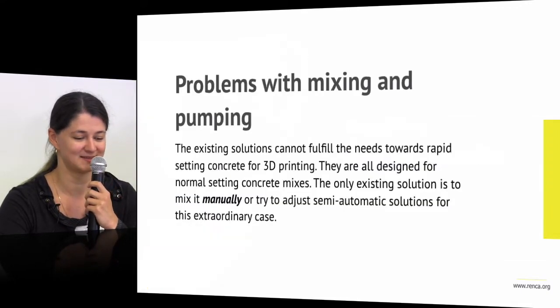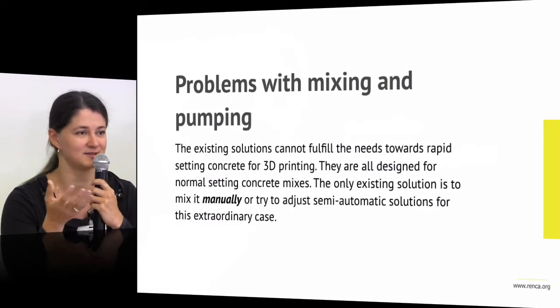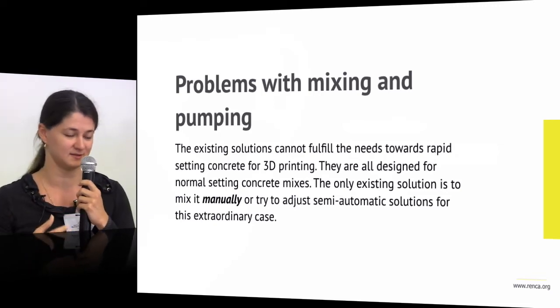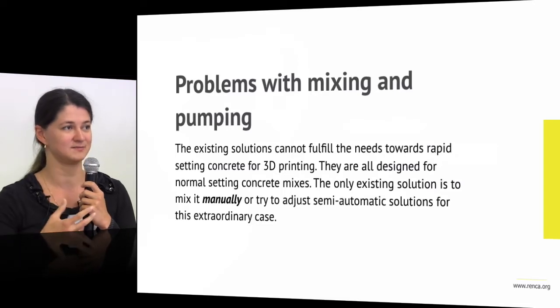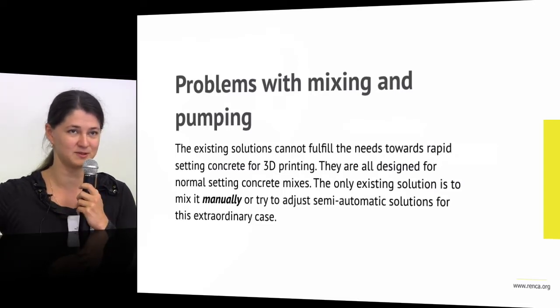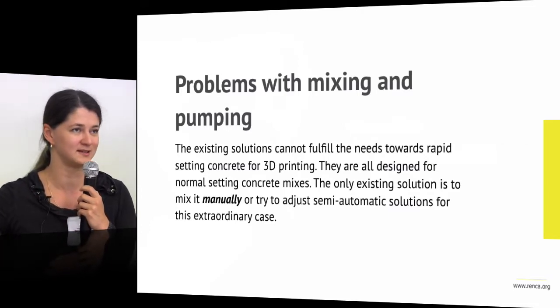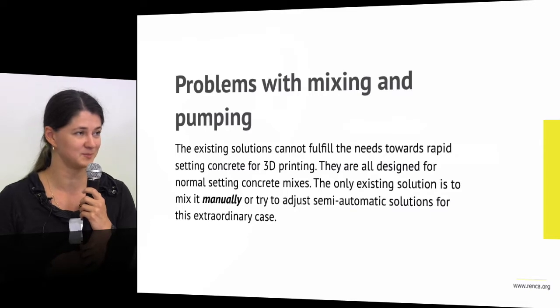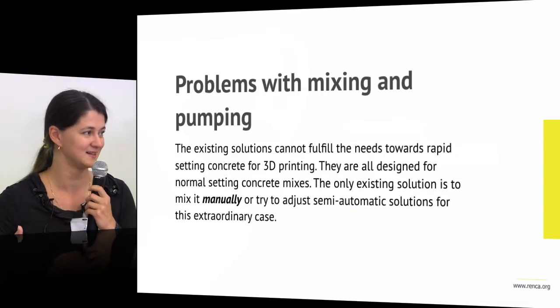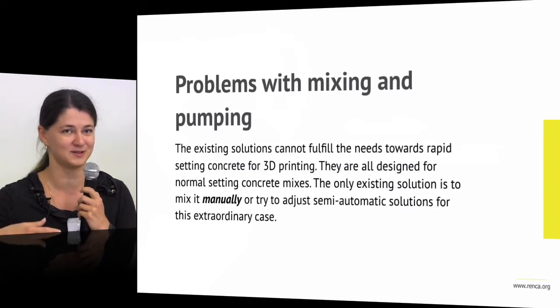What is the real state today? There are several issues in 3D printing. Coming from the material side, we see problems with the mixing and pumping machine. If you make a mix sticky enough to hold its shape when it comes out of the printer, and strong enough to be structural with good compressive strength, then you face pumping problems. The pump simply cannot be strong enough — the mix gets stuck inside the machine. You have to stop, clean, you lose time and a lot of money.